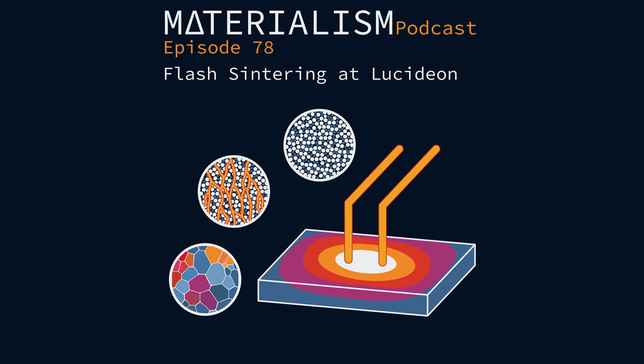Indeed. I guess the clever folks that work here, not me, I won't claim to have done this, have developed the nonlinear control software. Essentially, you tell it what to do and it will prevent any of those spikes within the tolerances you've told it to operate. So we can pulse current in, we can ramp it slowly, we can do all this. And when it spots anything about to localize, it'll back off that power system straight away and allow it to re-homogenize.